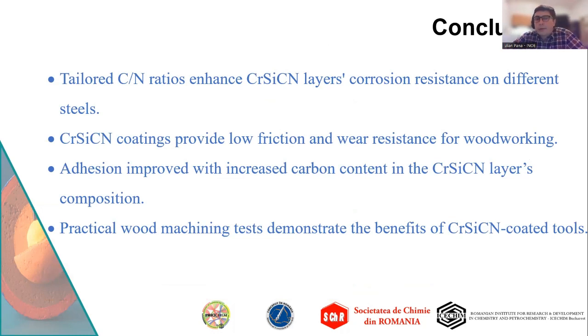As the conclusion, we have obtained tailored carbon to nitrogen ratios of chromium silicon carbonitride, and we have seen that the corrosion resistance is improved as compared to the steel. We have obtained low friction and low wear for woodworking applications. Adhesion is improved if the carbon content is increased in the chromium silicon carbonitride layer composition. Practically, wood machining demonstrated the benefit of using this type of coating, to replace tools less often or to cut more with a two-fold factor.